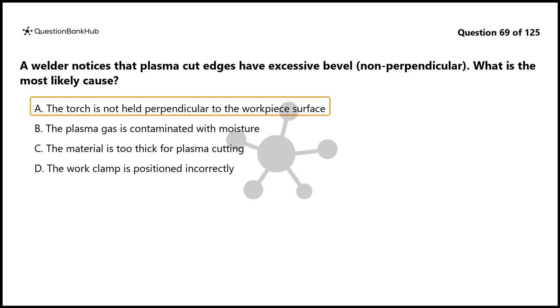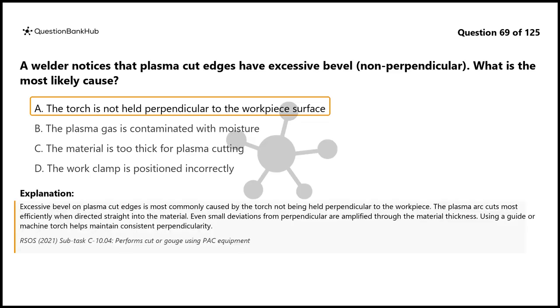The correct answer is A. The torch is not held perpendicular to the workpiece surface. Excessive bevel on plasma cut edges is most commonly caused by the torch not being held perpendicular to the workpiece. The plasma arc cuts most efficiently when directed straight into the material. Even small deviations from perpendicular are amplified through the material thickness. Using a guide or machine torch helps maintain consistent perpendicularity.